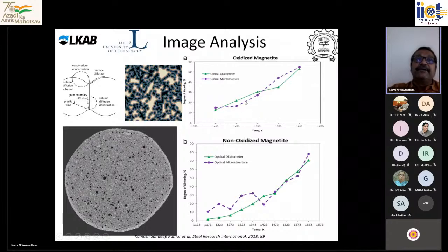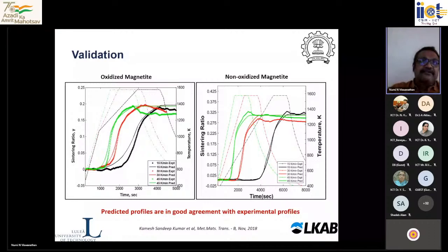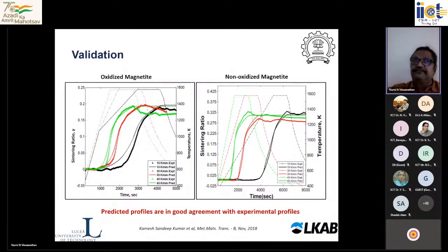And when we compared what is microstructurally obtained, looking at the powder, and what we measured at a macroscopic level, looking at the shrinkage, it was such a nice correspondence between these two. Okay? So we confirmed it at both levels. These are all very revealing, where we could see that yes, what we are doing is fundamentally fine. We were checking, at different scales, whether what we have understood is fine or not. And then of course now we can predict. Once we have the equation, there are ways to do it. I'm not going into the mathematics of these things, but I'm just telling you how we used mathematics, experimentation, and prior knowledge, all these things put together to come out with the prediction, and this is how well it predicts. Okay? This is as far as sintering is concerned.